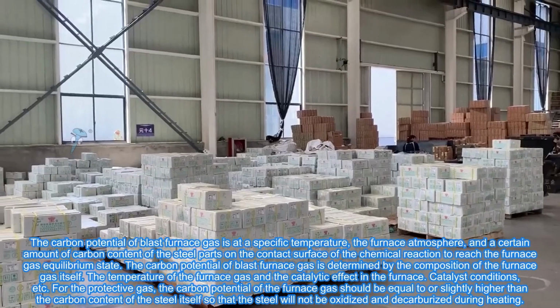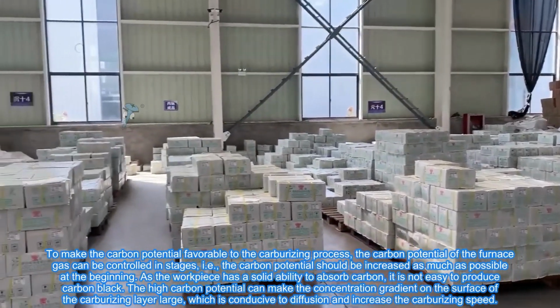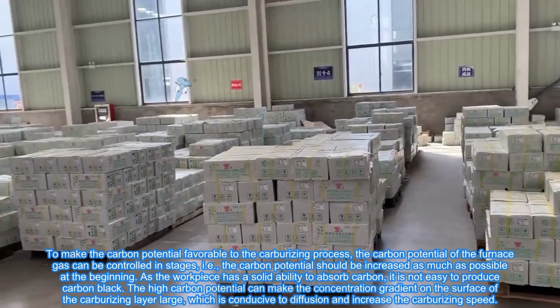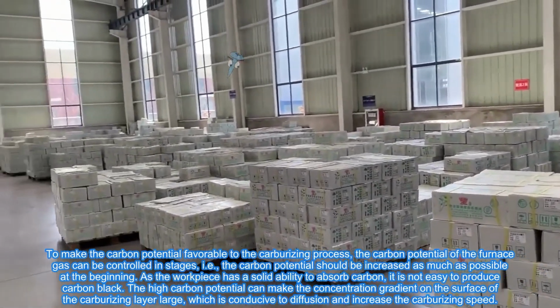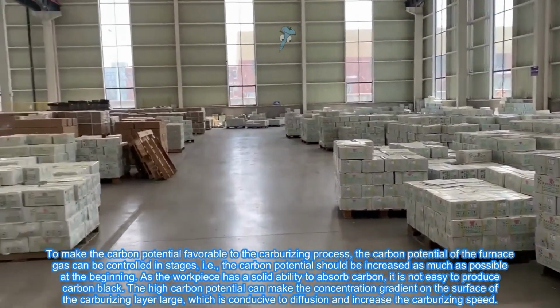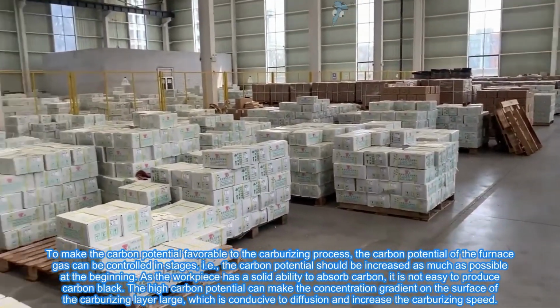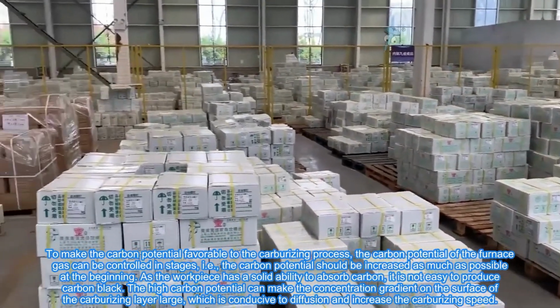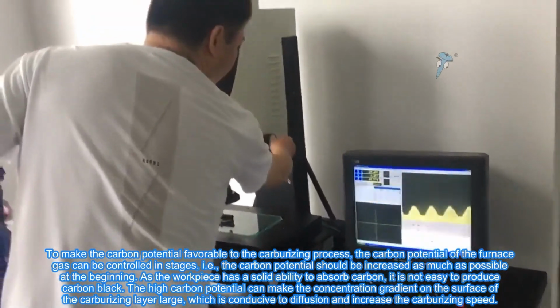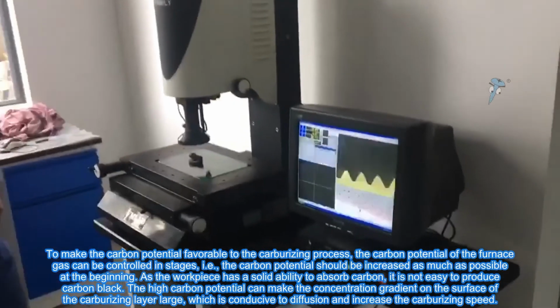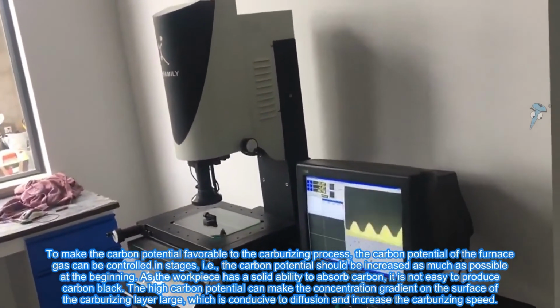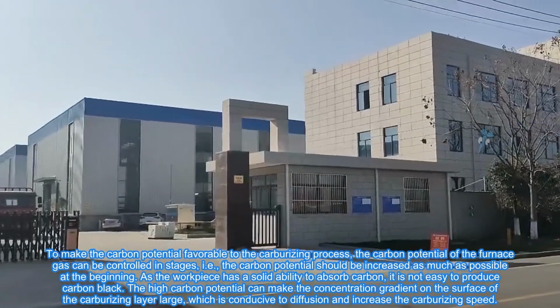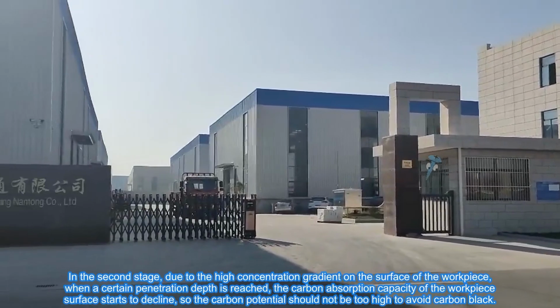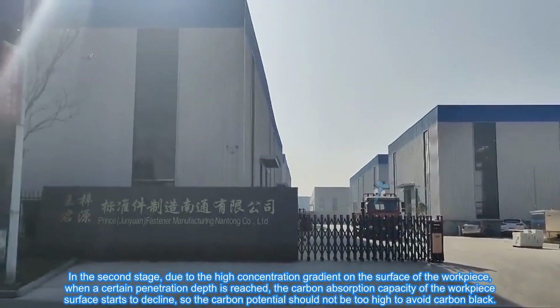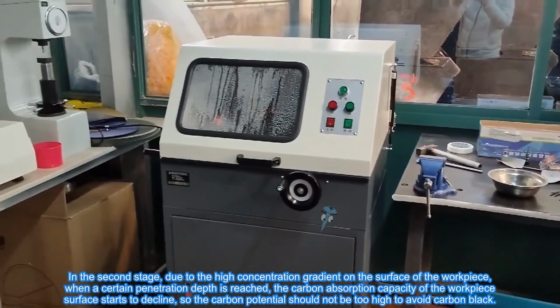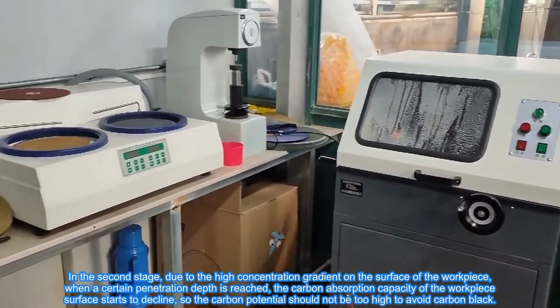To make the carbon potential favorable to the carburizing process, the carbon potential of the furnace gas can be controlled in stages, i.e., the carbon potential should be increased as much as possible at the beginning. As the workpiece has a strong ability to absorb carbon, it is not easy to produce carbon black. The high carbon potential can make the concentration gradient on the surface of the carburizing layer large, which is conducive to diffusion and increases the carburizing speed. In the second stage, due to the high concentration gradient on the surface of the workpiece, when a certain penetration depth is reached, the carbon absorption capacity of the workpiece surface starts to decline.